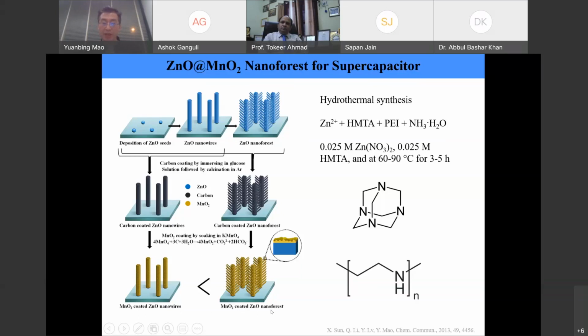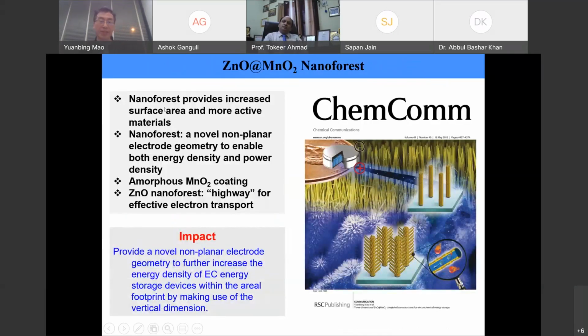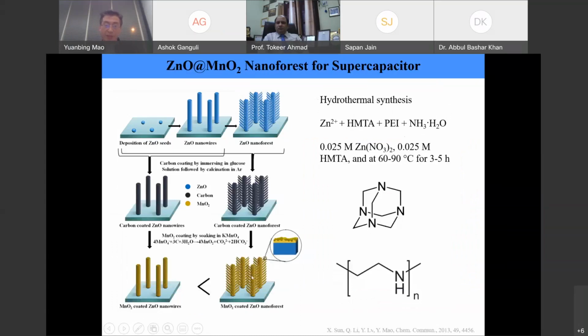either nanowire arrays or nanoforests. I don't want to show you the details of how the performance improved or how the measurements were done. But what we saw is that the nanoforest provides increased surface area and more active materials. The nanoforest serves as a novel non-planar electrode geometry to enable both energy density and power density. And this type of nanoforest has 5 times higher performance than the nanowire arrays.